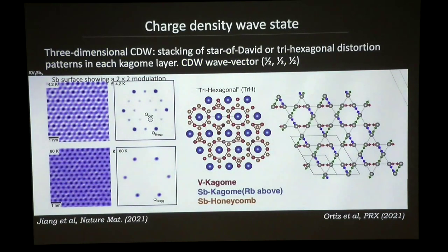So here is an STM image of the compound above the charge density wave transition temperature. Now we are looking at this antimony layer, and you can see these patterns here, that's what I showed you earlier. This is the honeycomb of the antimony. So there is no charge density wave here. This is a Fourier transform, and you just see the Bragg peaks.